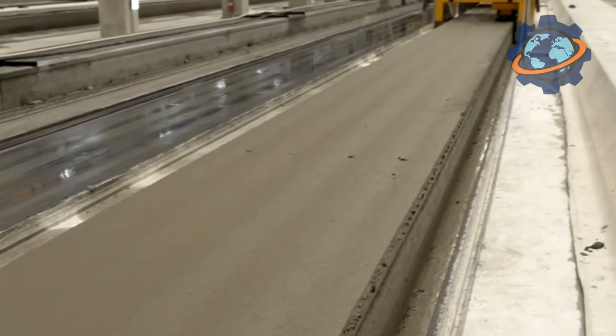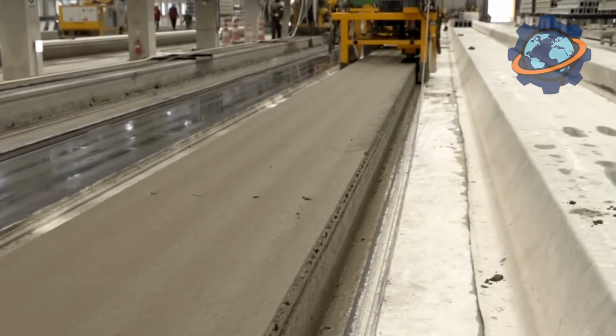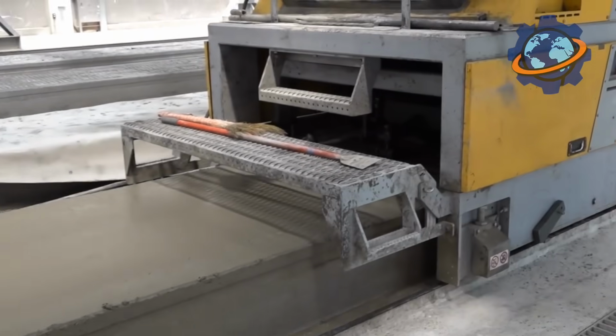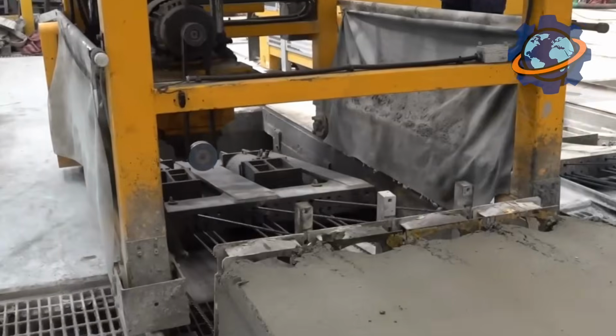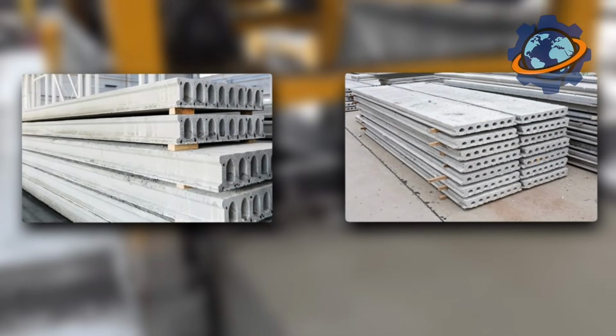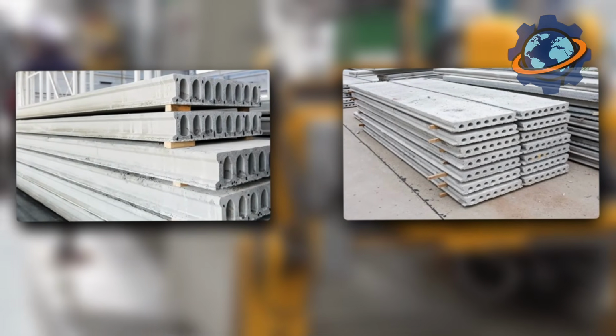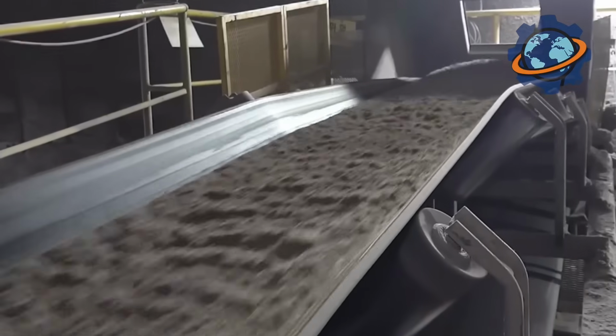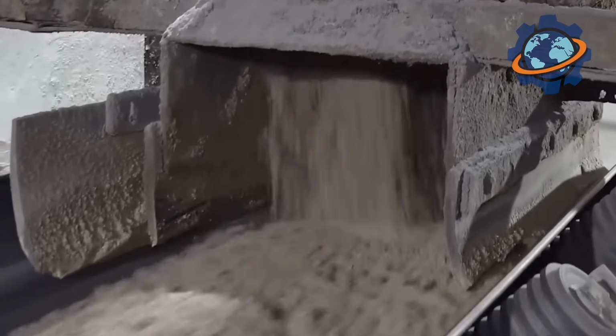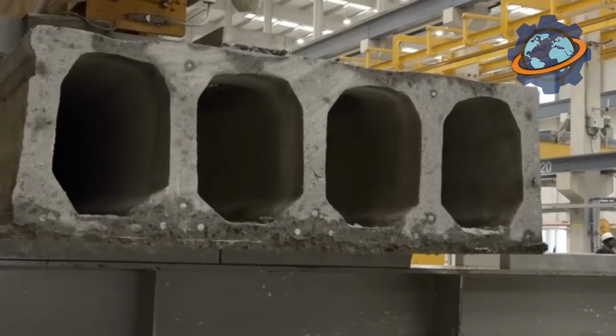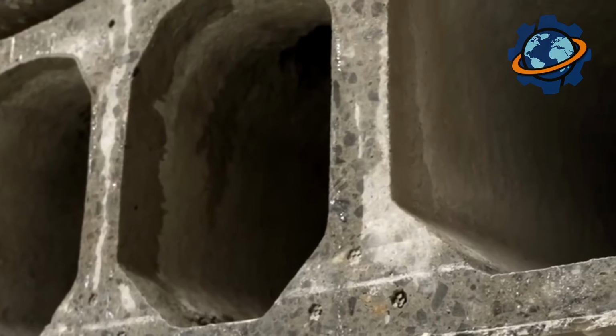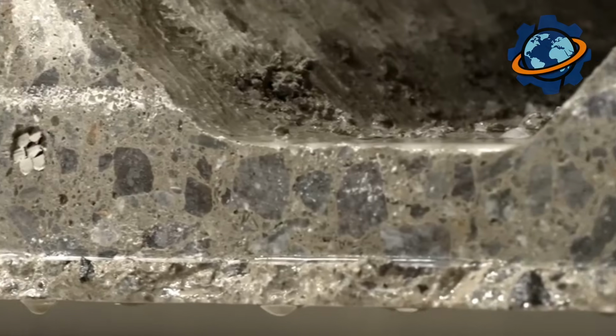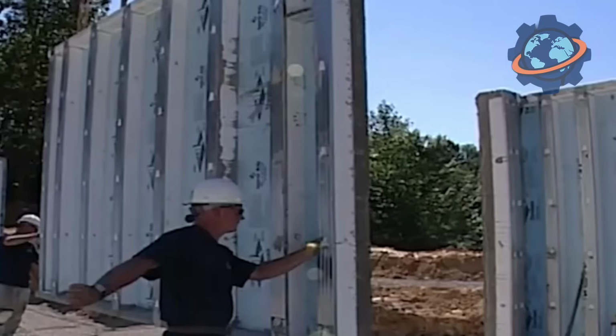The machine, like a giant concrete snail, slowly crawls forward, leaving in its wake a perfectly formed, endless concrete slab with hollow cores inside and tensioned steel muscles hidden within its body. Because the concrete is so dry, it holds its shape instantly and doesn't sag. This is secret number 2. The voids, which make the slab 50% lighter than a solid one while barely reducing its strength, as the top and bottom sections do most of the work.